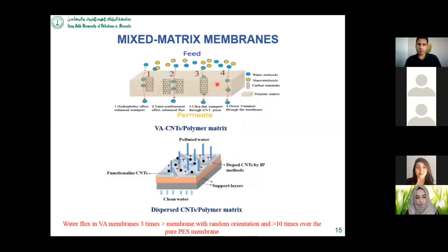This is the polymeric membrane modified by the addition of vertically aligned carbon nanotubes. Here you can see the various channels for the flow of water molecules through this composite membrane. The water molecules can flow beside the carbon nanotube due to hydrophobic effect, because the carbon nanotube is inherently hydrophobic. Of course, you can modify the surface and make it hydrophilic. Furthermore, the water molecules can flow through the space between the carbon nanotubes, and also through the interior of the carbon nanotube. But in this case, you have to remove the catalyst so that this channel is available for the flow of water molecules. And of course, water can also flow through the polymeric matrix itself.